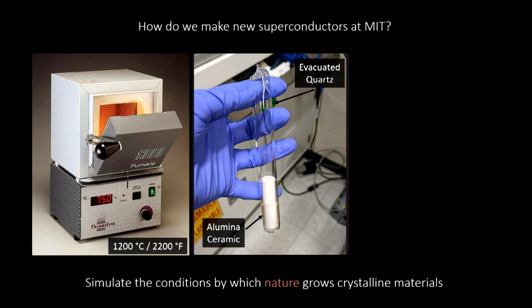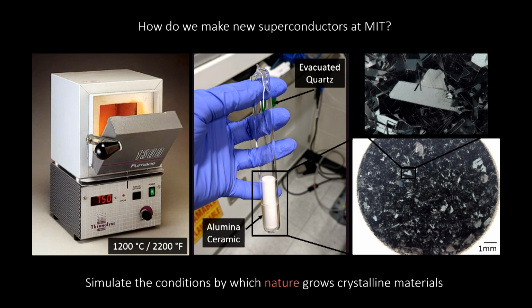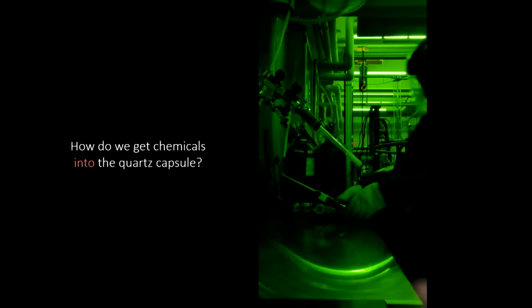When you use the right chemicals and combine them over the right temperature profile, you can grow beautiful single crystals, which albeit are much smaller than those found in nature, because I had something like 2 weeks to grow these, and Mother Nature took millions of years. In preparing this talk, I got some really awesome questions about this middle image right here. Here are all my chemicals down at the center, double sealed in this quartz ampule. A natural question I got was, how do you actually put the chemicals inside the quartz tube? How do you get them inside for this chemical synthesis process? The answer is that we use an oxyhydrogen torch.